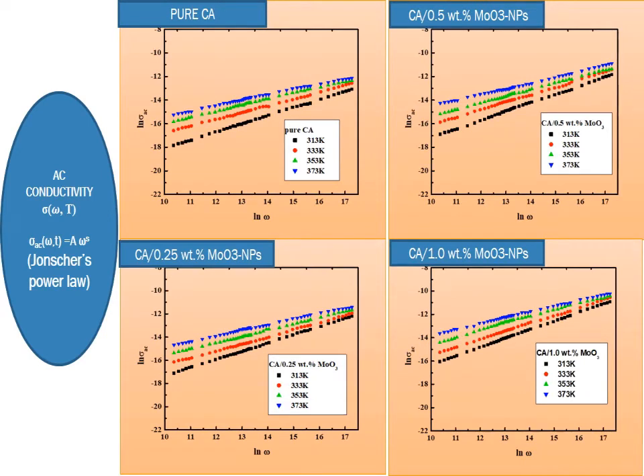Here the AC conductivity is drawn as a function of frequency and temperature, and it was observed that it increases with temperature and also with frequency. Also, it was observed that the AC conductivity increases with increasing concentration of molybdenum trioxide, as we see in this figure. And by using Jonscher's power law, we can calculate the frequency exponent S from the slope of these curves.